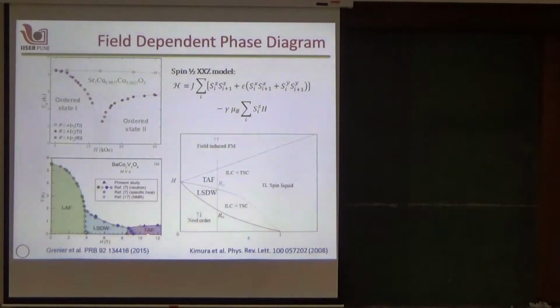And in the TAF phase, the transition temperature indeed increases with increasing magnetic field. Now what is interesting is that we can get this behavior, if indeed it is this behavior, by just putting 0.25% of cobalt impurities in this Heisenberg like chain. So we are getting the Ising like behavior. Now if we look at the vanadium system, it is also a chain system. So here cobalt is spin half, vanadium is, it's an Ising like chain.